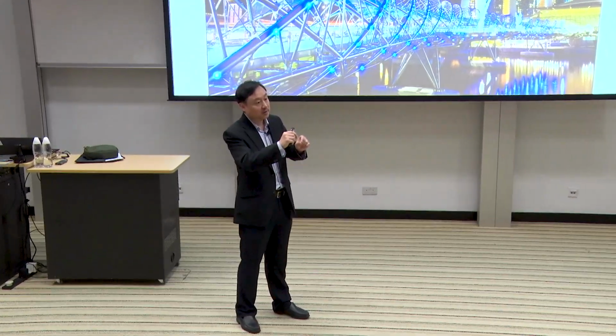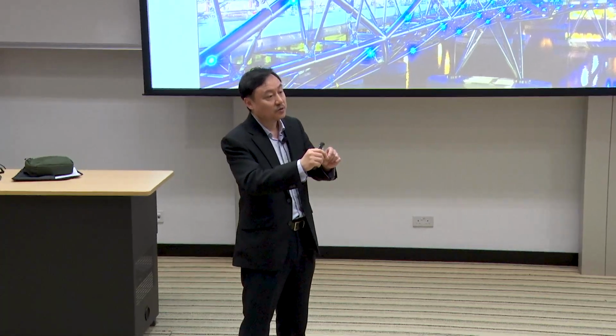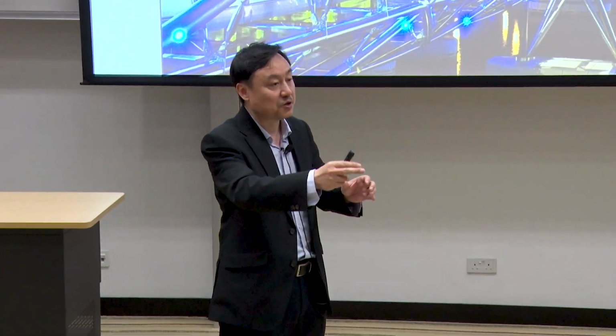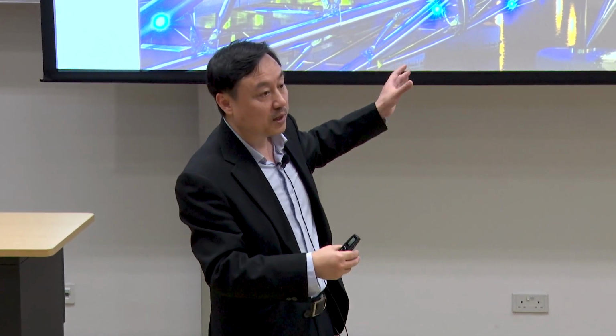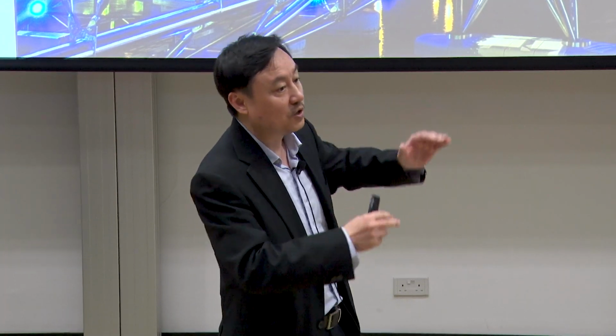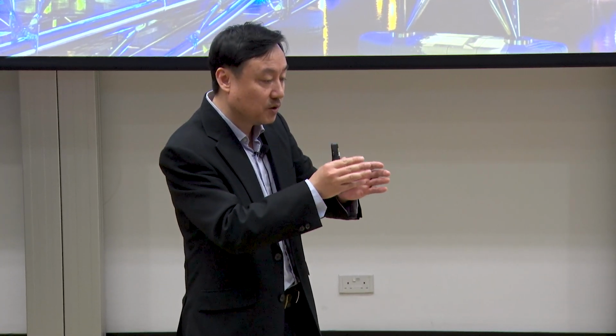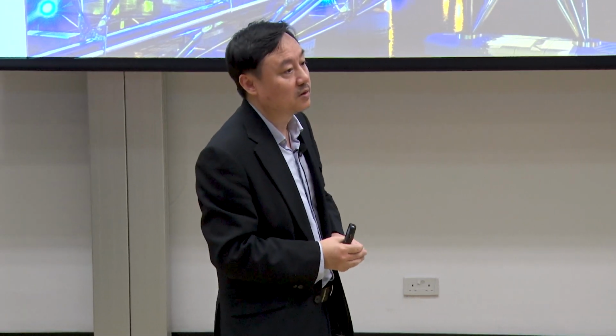In different layers, we play with the dopant concentration or combination. So it's a lot of work. Actually, we have done all the experiments you mentioned. Then we try to solve the mechanism issue here, because if you get insight, you can tune the core-shell structure to achieve what you want. We actually did a lot of simulation. Numerical simulations have become a key part of our research, especially since there are so many energy levels and so many energy transfer pathways. That's why numerical simulations can really help us understand the energy transfer, not only between the lanthanide dopants but also between the ions in different layers. So that's actually a very systematic study.